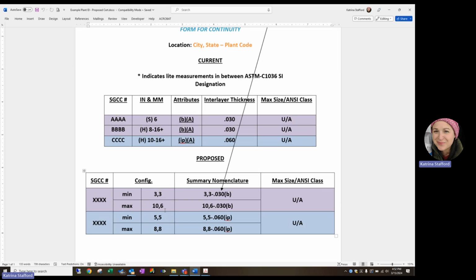So for this product, if a fabricator wished to have no cap and to be able to make any configuration, we would recommend that you send in an 8mm piece of glass, an 8mm piece of glass with an 030 PVB interlayer. Test it once, and if it passes, your certification will be updated. Similar to how LAMI is currently certified, each interlayer code must be certified separately.